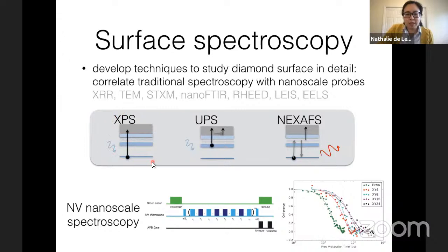But we ended up landing on a bunch of photoelectron spectroscopy tools. So this is X-ray photoelectron spectroscopy, ultraviolet photoelectron spectroscopy, and near-edge X-ray absorption fine structure spectroscopy. All of these techniques basically give you some probe of either the density of states or the density of unoccupied states, and you get your surface sensitivity by relying on the very short inelastic mean free path of electrons coming out of the material.